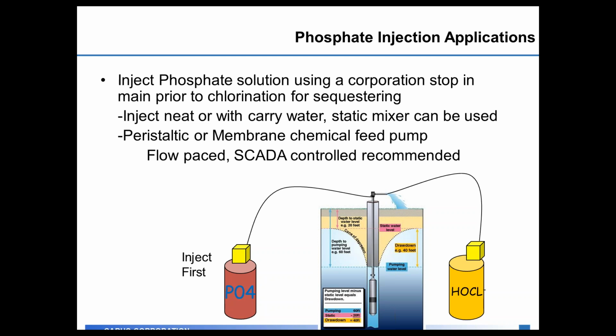Once the iron and manganese is precipitated, you can't resequester it back into solution, and you'd have to filter those solids out. Typically, phosphate products are fed neat directly from the container. You don't need to add carry water unless you want to. A good rule of thumb is that for every inch diameter of the pipe that you're going to inject the phosphate in, you would like a distance of 1 foot between the two contact points, with phosphate being first. If you had a static mixer, you can shorten that distance, but phosphate blends in readily with the water.